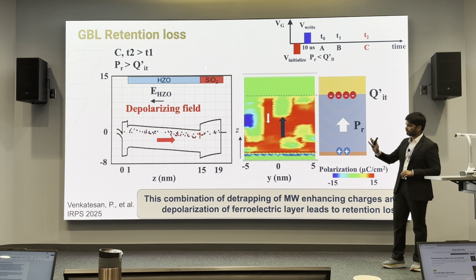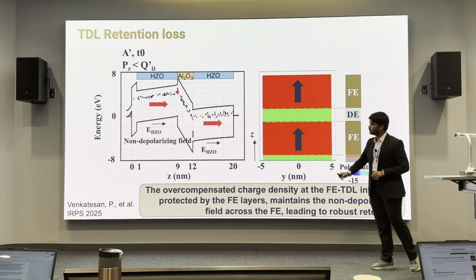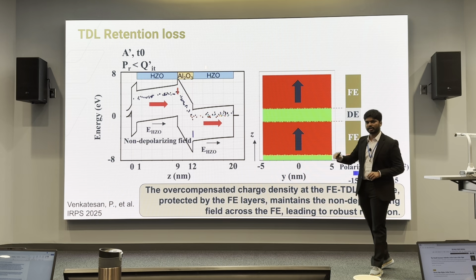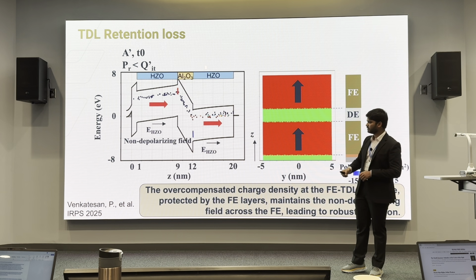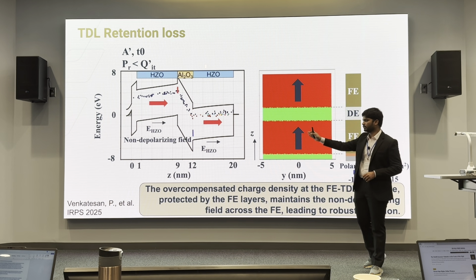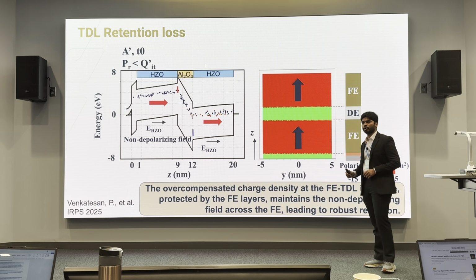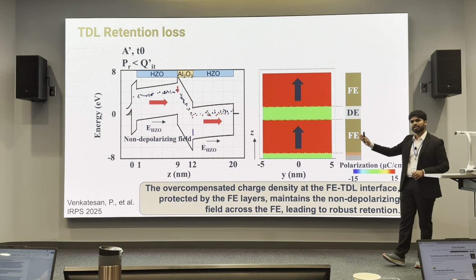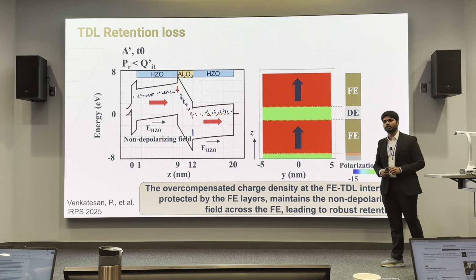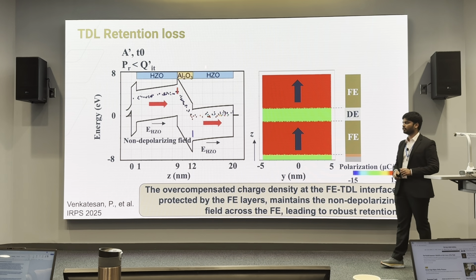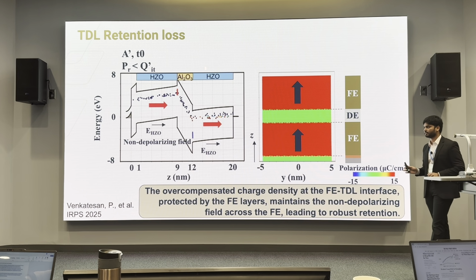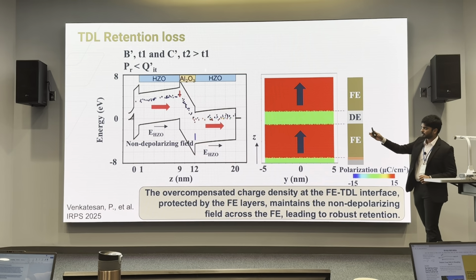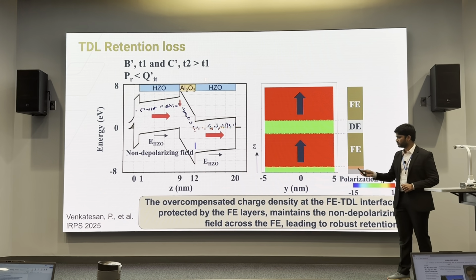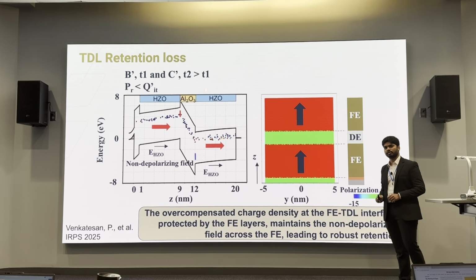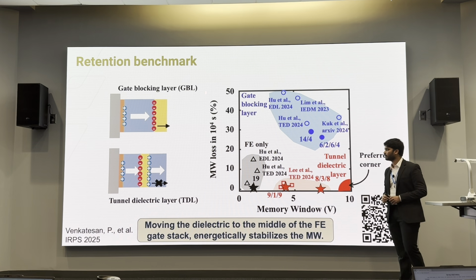So what happens when we move the dielectric to the middle? In this example, we have moved the dielectric back to the middle, and we see that the thick HZO layers on either side, the 8 nanometer HZO layers, prevent the detrapping of the charges and hence prevent the second step, the depolarization of the ferroelectric layer, from taking place. So even after time immemorial, this stays the same.